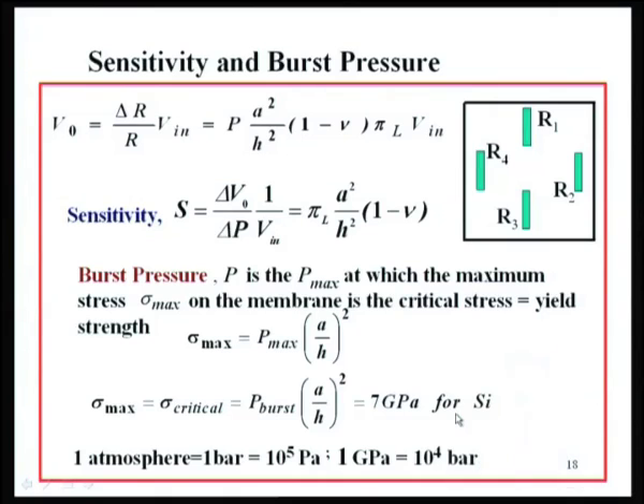See, for example, if I keep on increasing the pressure on this membrane, the maximum stress is experienced at the edge, which is applied pressure into A by H whole squared. So, I can go to a maximum pressure. At a particular maximum pressure, the stress at the edge will reach a maximum value, which will be the critical pressure. That is the point at which the membrane will yield, it will burst. Okay. So, that critical pressure is 7 gigapascal for silicon, that is 70,000 atmospheres. So, the maximum pressure that you can apply will be decided by when the critical pressure is reached.